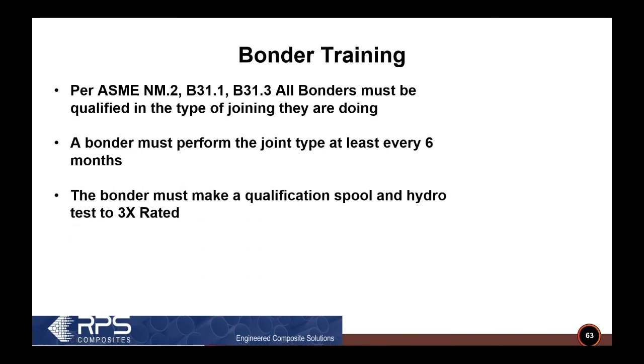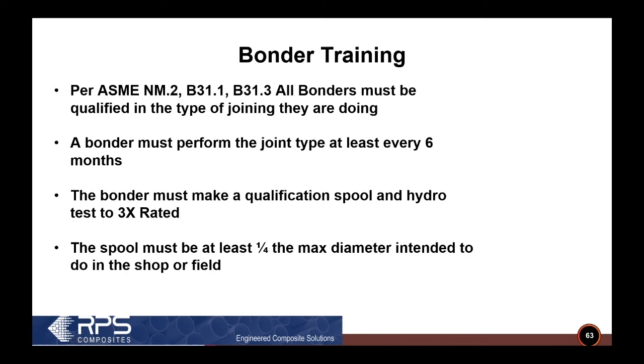So what the bonder does is they make a qualification spool on the type of joint they're going to do, and they pressure test that joint to 3 times rated. The size of the joint they do has to be a quarter of the maximum size they'd like to do in the shop or in the field. So if I do a 12-inch joint in my qualification spool, I'm qualified up to 48 inches.